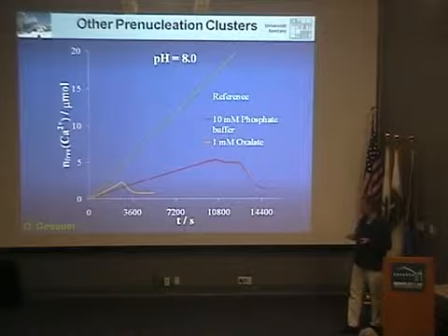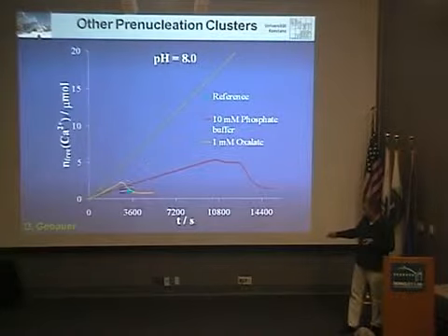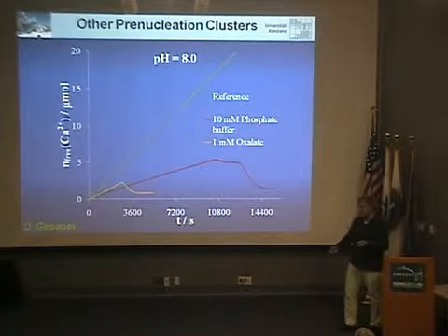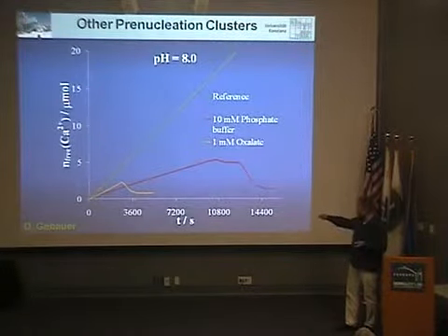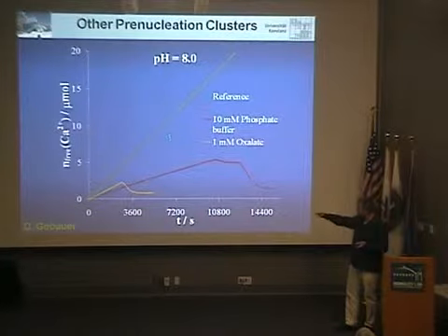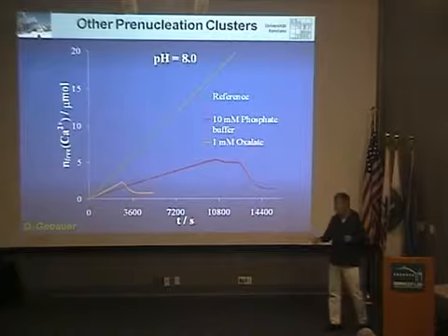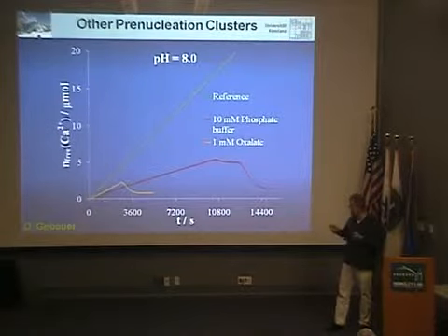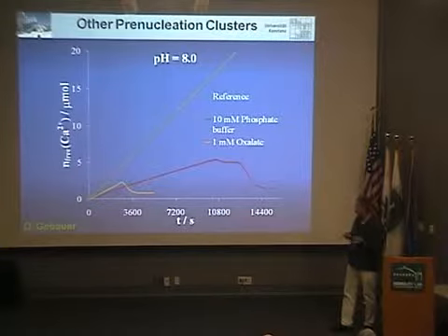So, first we looked at different biominerals. For example, we did the same experiment with calcium oxalate, and that's the yellow curve here. And again, you get the same story as calcium carbonate. You get formation of clusters, which you can see in the ultracentrifuge. You can do the experiment with calcium phosphate, that's the red curve, and you see cluster formation again. And Nico Sommerdijk published a few papers quite recently, beautifully showing the clusters in electron microscopy for calcium phosphate. So it seems that at least for biominerals, the clusters are relevant.